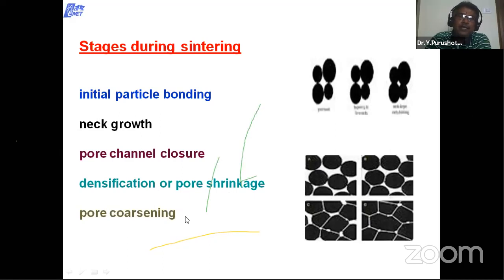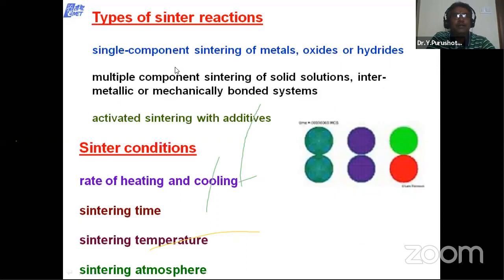If you increase the temperature or the sintering time, and expose your material for a longer duration, pore coarsening will also take place. These are some of the pictures of the different stages during sintering. And there are different types of sintering reactions also: single component sintering of metals, oxides, and hydrides; multiple component sintering of solid solutions, intermetallic or mechanically bonded systems; and activated sintering with additives. And these are the conditions.